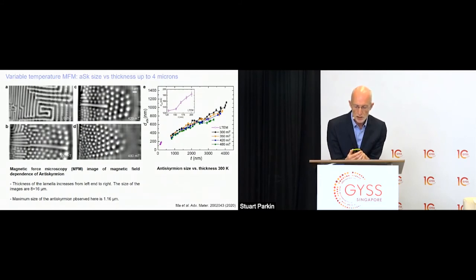And the size of these objects also depends on the lamella thickness. And without going into any details, this is because of long-range magnetic dipole fields that depend on the thickness of the lamella.